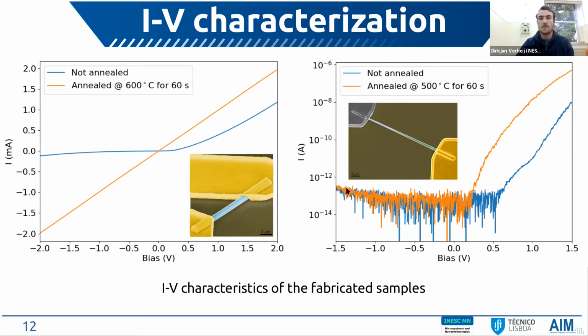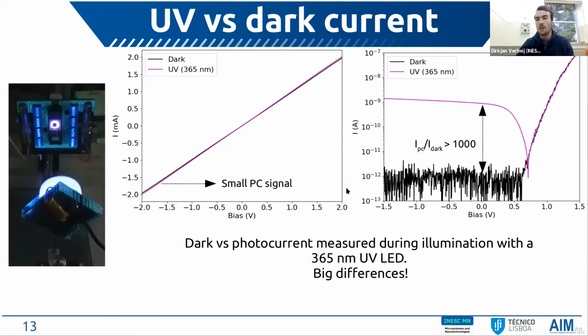So then before irradiating our samples with protons, we always like to do some photoconductivity studies, because protons damage the device and UV doesn't. So it's always a good way for us to see the properties of the device and how they behave when illuminated by UV light. So in this case, we use a UV LED with a typical wavelength of 365 nanometers.